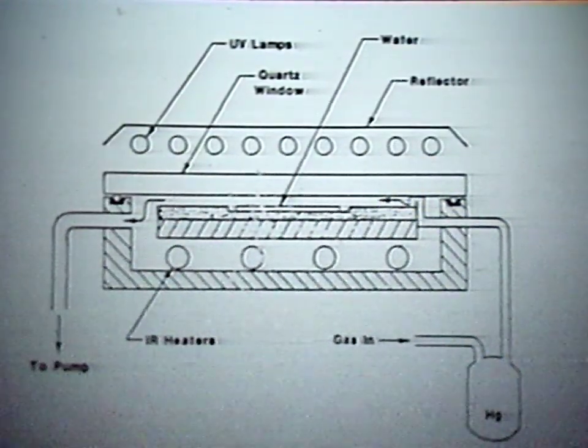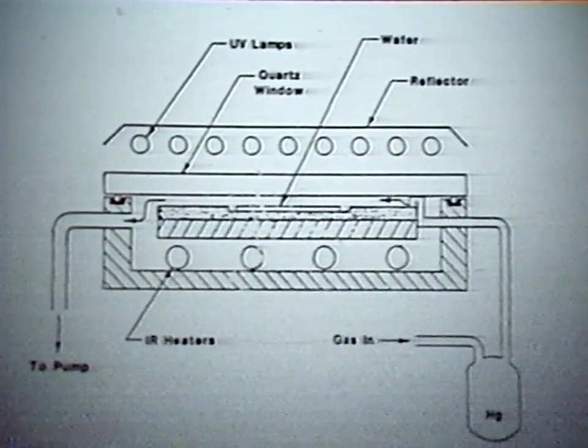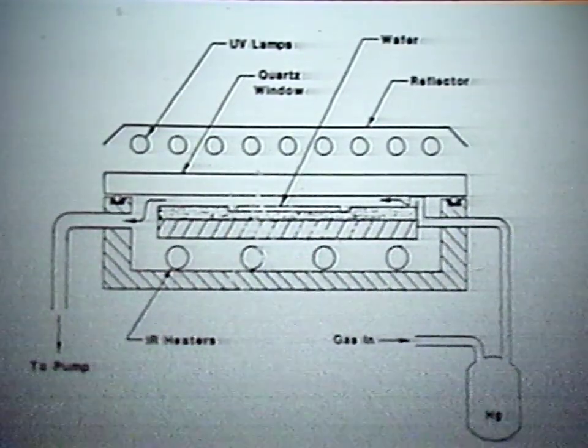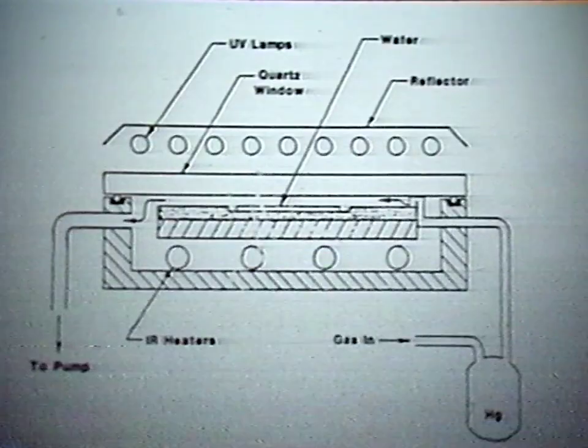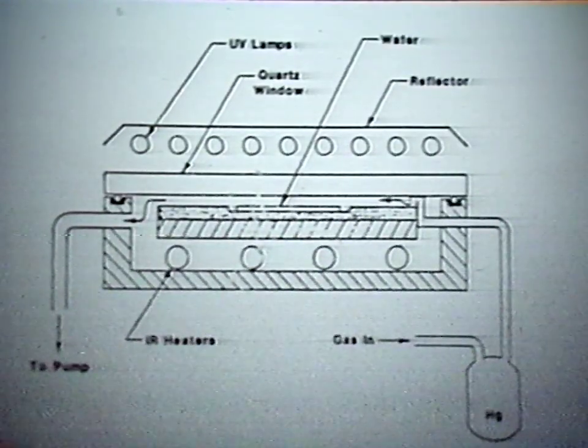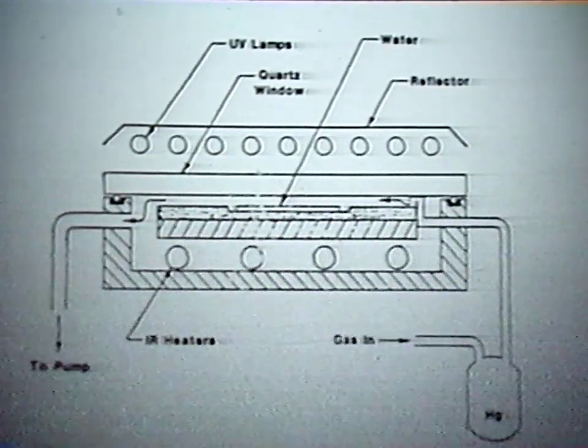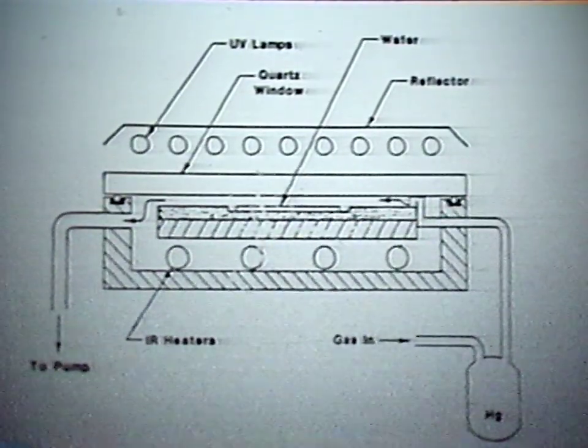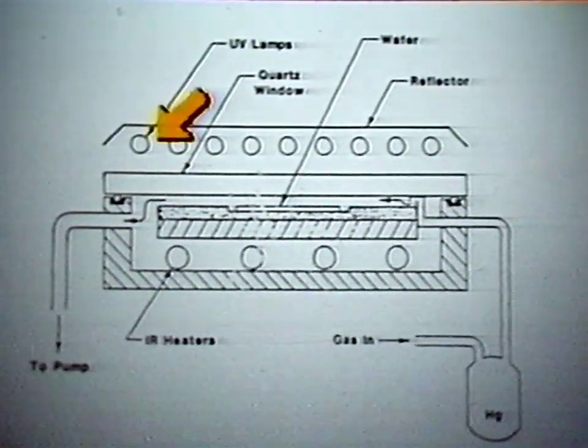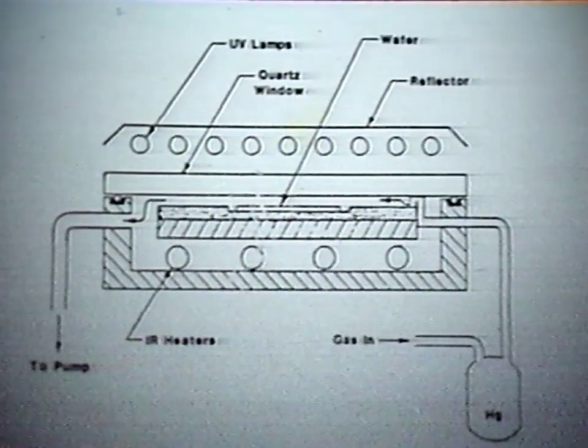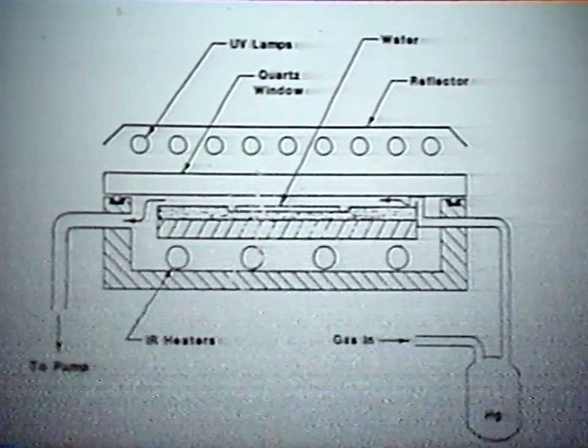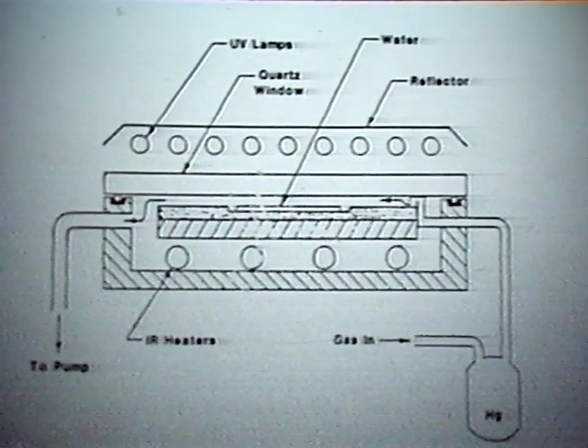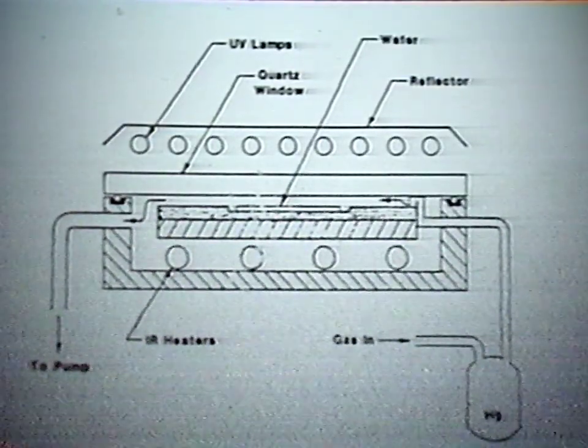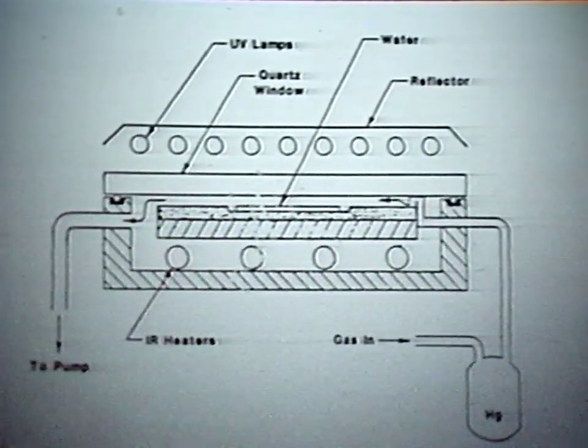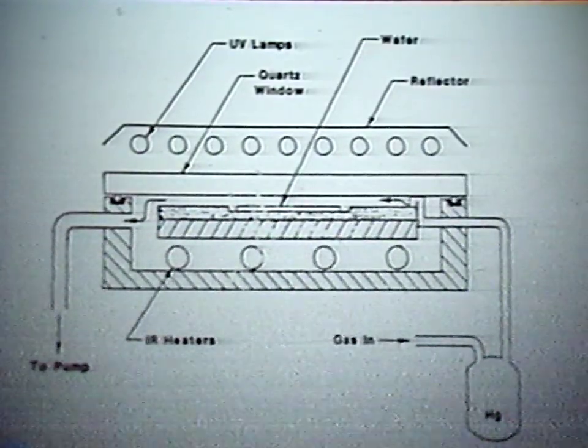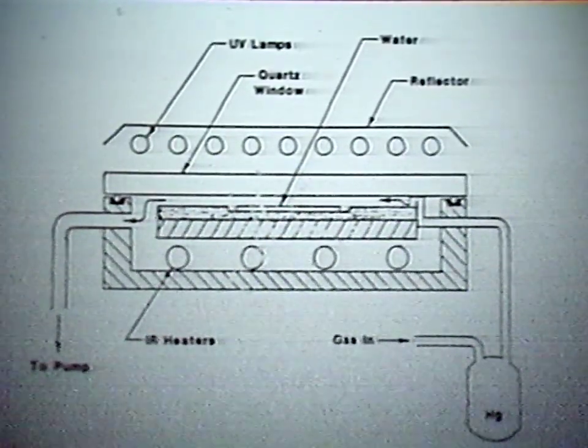And in this case now we have a fairly closed space situation where we have a quartz plate close to the substrate surface, and the ultraviolet lamps positioned above here in as close proximity to the substrate as possible. That will give us the radiation needed to have the reaction taking place. And after the reactions have been completed here, the gas passes, as shown here by the arrow, down the